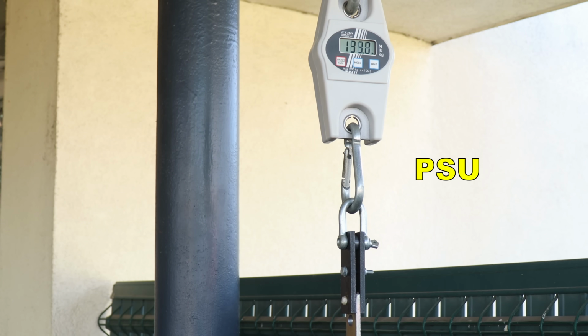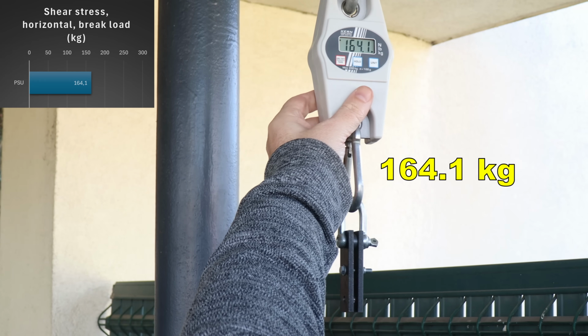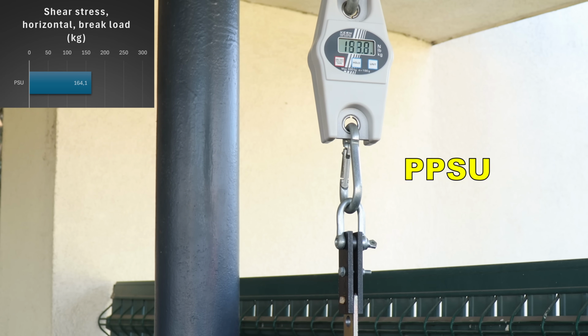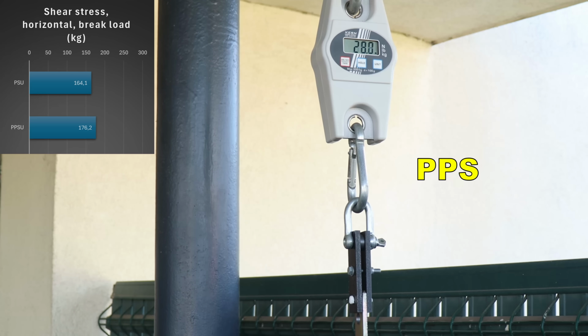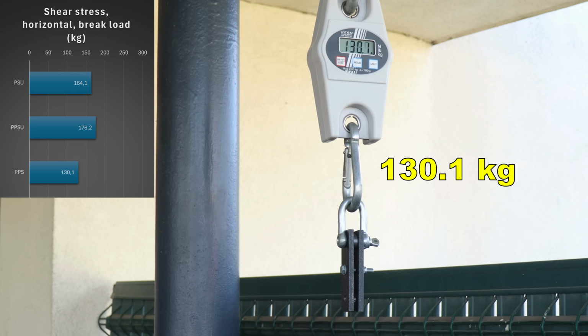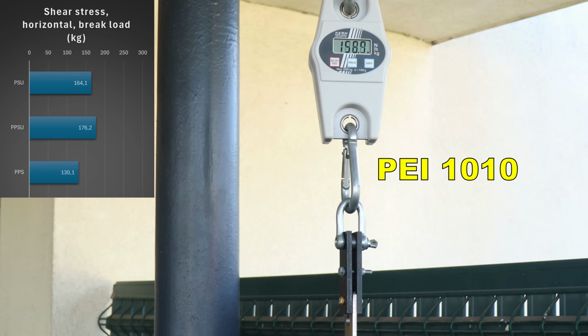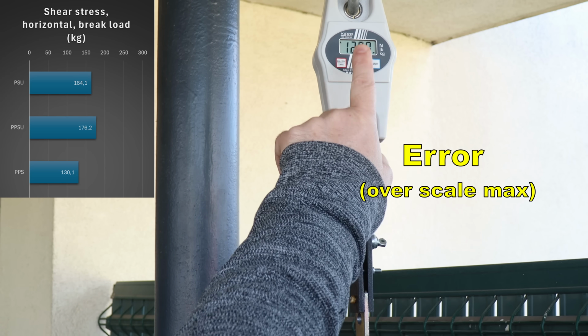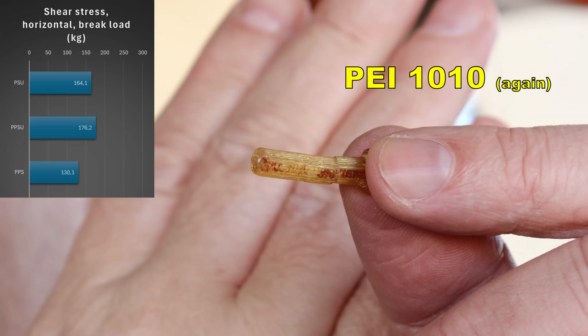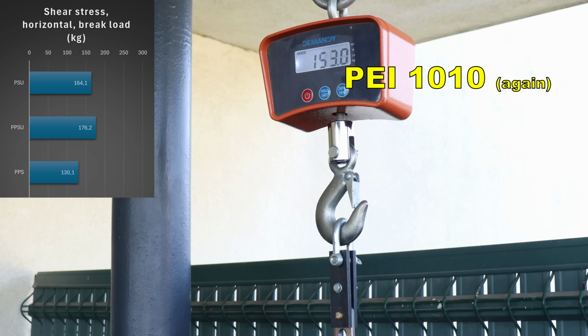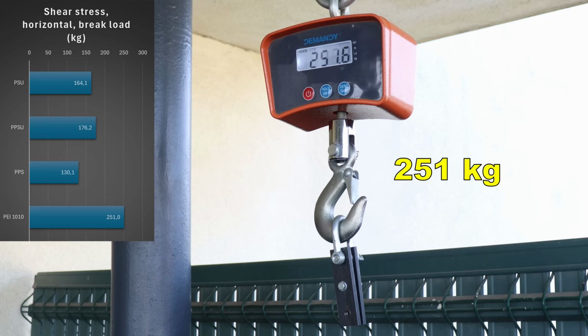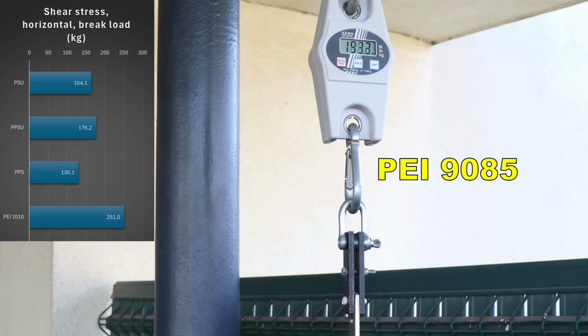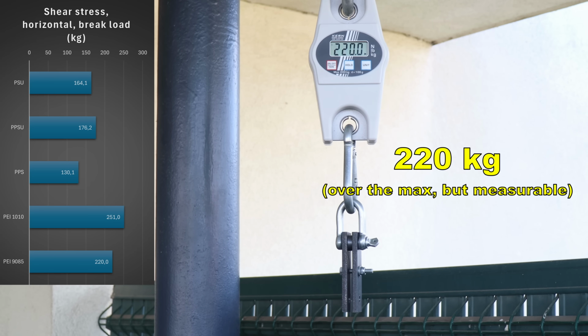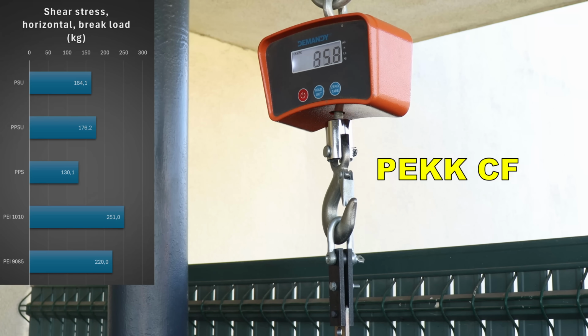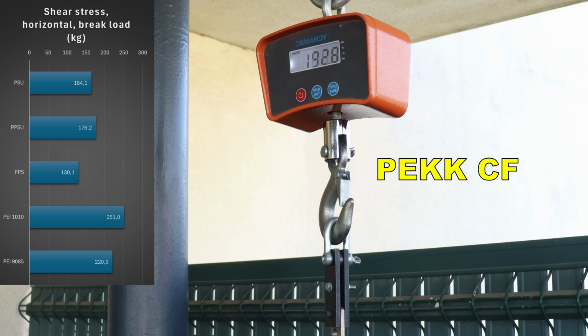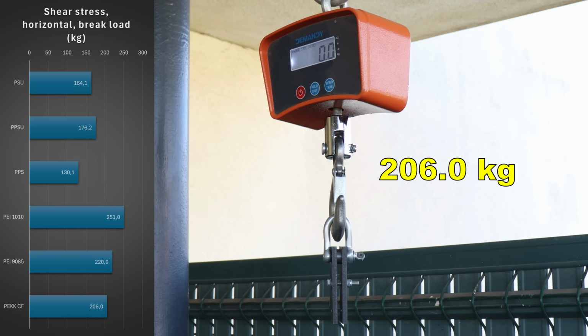Two-sided Shear test, and these test objects are printed in horizontal position, and the maximum of this hanging scale is 200 kilograms. And the first material, which was too strong for this scale, and this is how it looks like after this attempt. I switched to the crane scale, and this time it was broken. This was over the max too, but still measurable. And I was ready for the PEKK-CF, slightly above 200 kilograms.